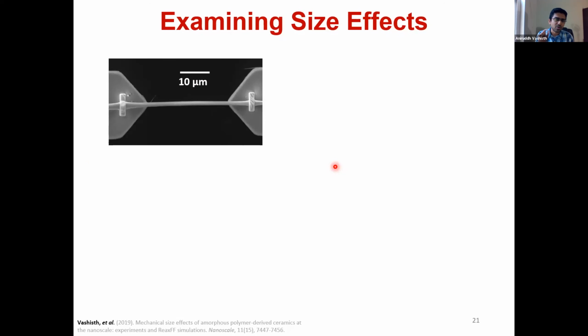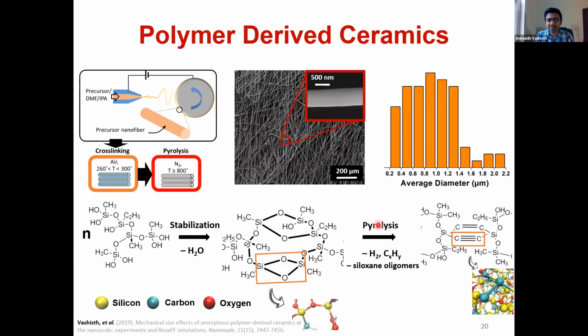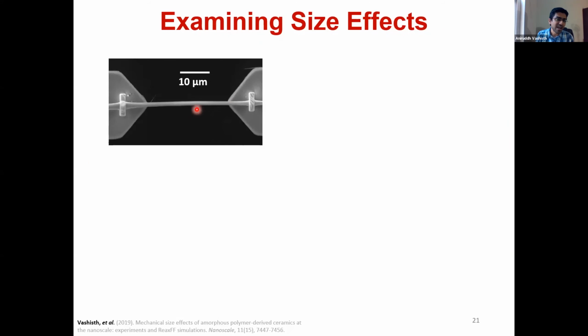What we wanted to do was look at the mechanical strength of these fibers, and this whole research project was motivated by the fact that you have these gases that are evolving during this whole process, and how do these gases play into the final mechanical strength of your material. So for example, if you have this fiber that has been made and you're trying to cook this fiber, the gases would try to come out from the center to the surface of the fiber. But at the same time, there's a competing mechanism that's going on. The fiber is actually solidifying on the periphery as well. So you have gases that are coming out, and you have fiber that is solidifying at the periphery. So there are two competing mechanisms, and we really wanted to know how exactly these two mechanisms are competing with each other.